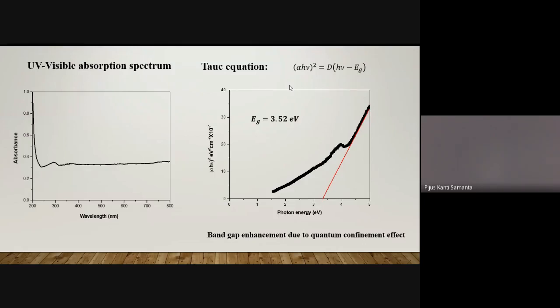This graph shows the UV absorption spectrum of the sample, which shows the low absorption property of the material. That means the material is quite transparent, especially in the visible window. And we can use the Tauc equation to calculate the band gap from this UV visible data, where alpha is the absorption coefficient and Eg is the band gap of the material.